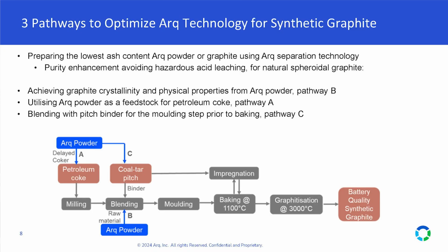And the Arq carbon, we believe, is a good precursor with low ash for the volatilization, which brings down the ash values by an order of magnitude. So this is obviously very preliminary from our studies, but we wanted to see if this was the way forward. So we have worked with the Western Research Institute and a few other big American universities on looking at three particular paths for introducing our Arq powder into the supply stream.